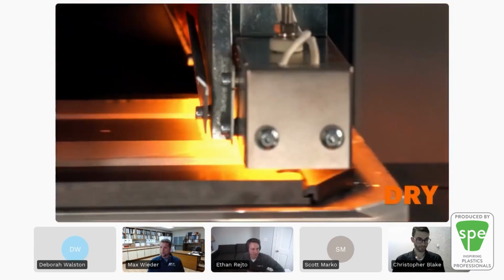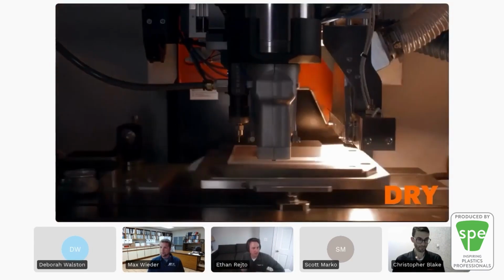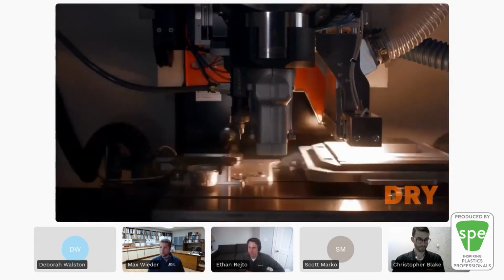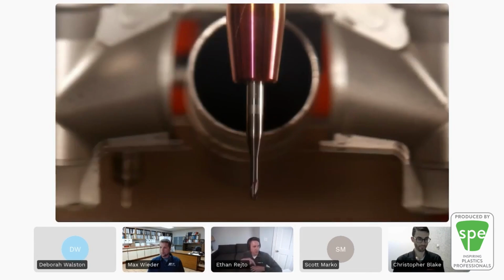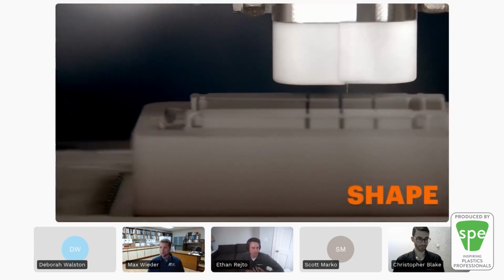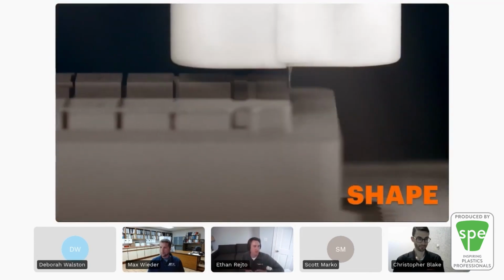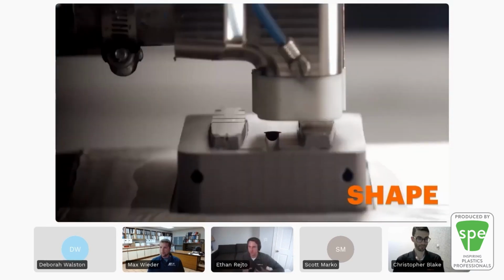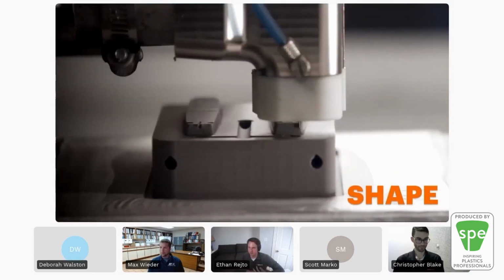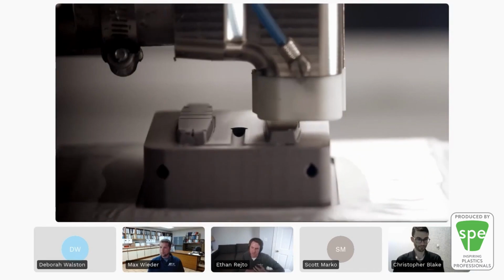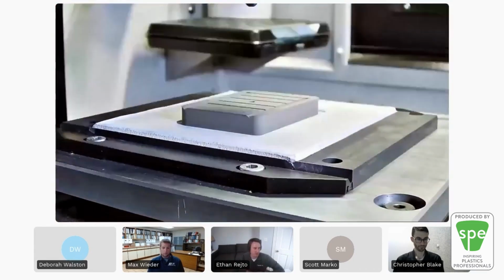We're then going to come through and dry it. That's going to firm it up, remove the solvent out of the material, and then every single layer is going to be machined, either perfectly flat or contour milled with a variety of different cutting tools to refine the shape, to improve the surface finish, and really clean up the design here. So this process repeats over and over again to build up your part.